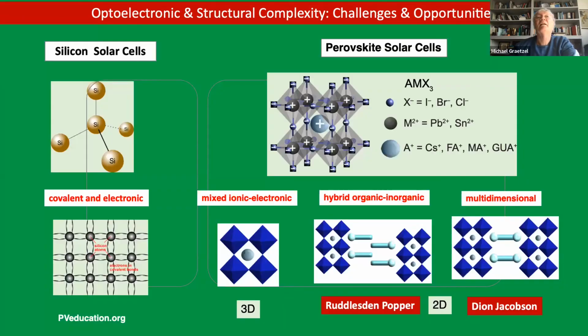So, going back to the perovskites, you can see the compositional complexity. You have a lot of choices for the anion, the central cation, and the A cation, but not all choices are suitable for visible light. You want to use iodide or iodide-bromide mixtures, and lead. Both lead and tin are being used. The tin cells are now reaching 15%. The lead cells are still ahead of the tin cells, but there's very active research in the tin field because people want an option to change from lead systems to lead-free systems.